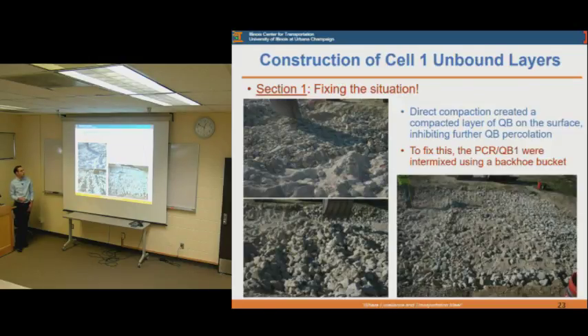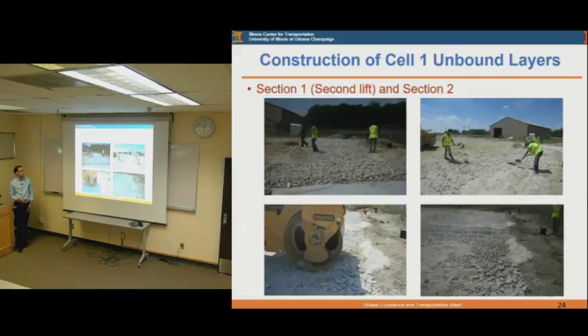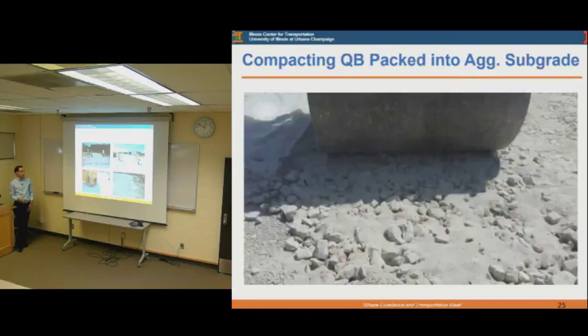So we had to somehow fix the situation, and in order to do that, we used the bucket of a backhoe loader to mix the two materials together. We were inspecting the difference between the lab and the field, and we found out that if we put the whole amount on the top at one time, we compact the Quarry byproduct in a layer instead of getting it inside, and the vibratory effort matters as well. So we need a larger vibration instead of the small vibratory roller we were using. We investigated that for the second layer of the 2-lift construction, as well as for the 1-lift construction test section, where we applied the Quarry byproducts incrementally instead of putting the whole amount on the surface at once, and we also used a larger roller compactor.